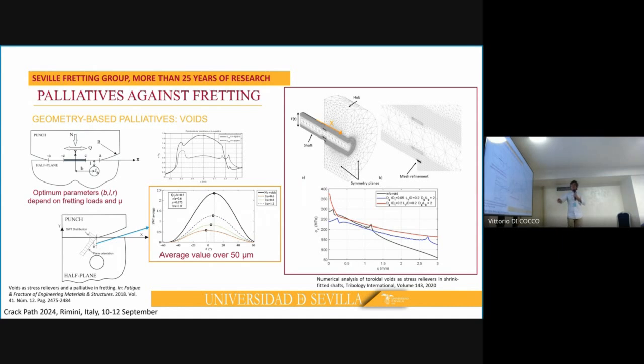In this plot, we can see the mean value of the Smith-Watson-Topper parameter along a line with different angles, starting from the most damaging point, the hotspot point. We can see that in contrast with the no-void case, when you introduce the void and depending on the geometry, we can observe an important decrease of the mean value of the Smith-Watson-Topper parameter along this line.